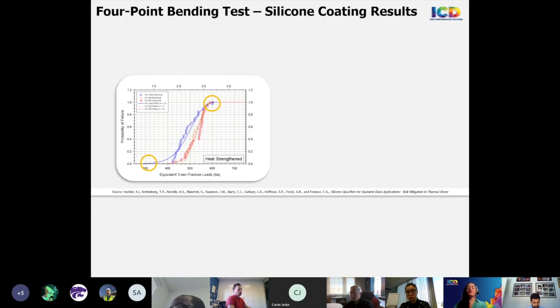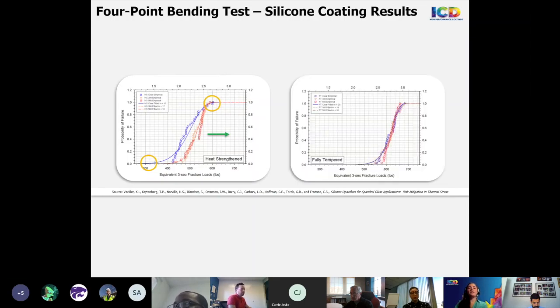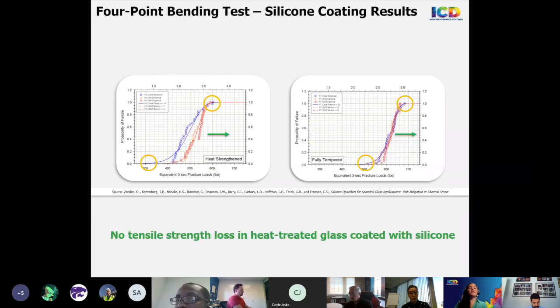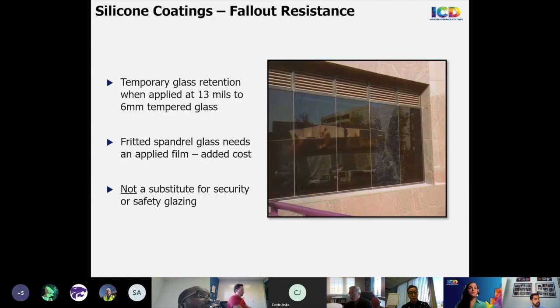And the orange-red curve shows us the probability of breakage for heat-strengthened glass with a silicone. Loads are slightly higher than uncoated glass, therefore significantly higher than what we saw of Frit. And then we have the tempered glass samples, and with uncoated, you hit 100% at around 680, while the orange-red line shows that silicone holds a similar load, but there's no weakening effect and still is higher than that of ceramic Frit. The conclusion is that there's no tensile strength loss in heat-treated glass coated with silicone.